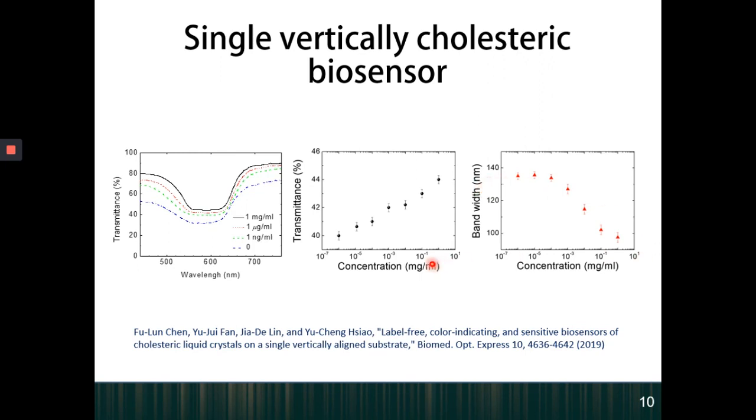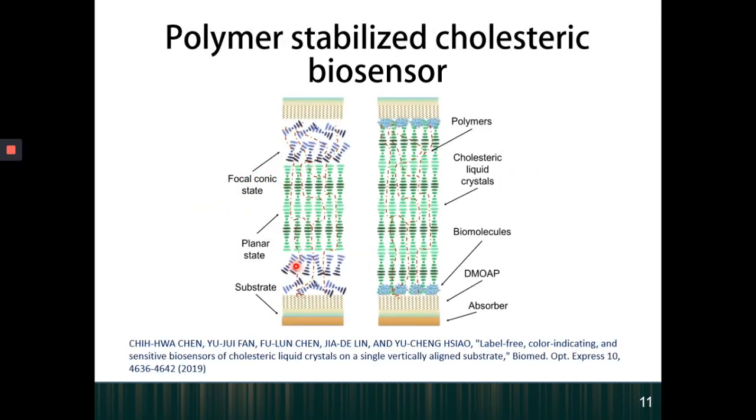However, the most important thing is that with the single vertical substrates used in this research, you get the linear behavior here, which makes the liquid crystal biosensor more promising to commercialize in the future. And we try to make the devices more stable, so we put polymers inside the devices to stabilize the liquid crystal biosensor here.